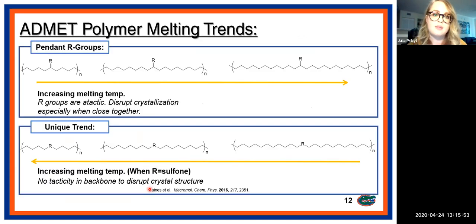I want to mention now some ADMET polymer melting trends, because this is one of the quick ways that we can determine if something is semicrystalline or amorphous. So when the R group is pendant to the chain, as in this top case here, as we move the R groups farther and farther apart along the polyethylene backbone, the melting point increases. And the reason why is because the R groups are atactic. So they tend to disrupt crystallization, especially when they're close together. So the farther you can space them out, the higher the melting point will be, because the polyethylene segments want to crystallize with each other.